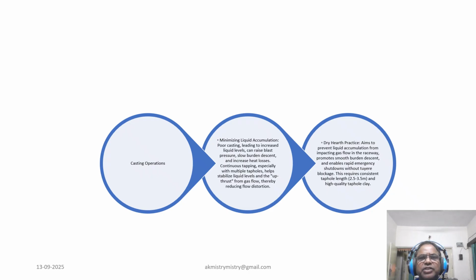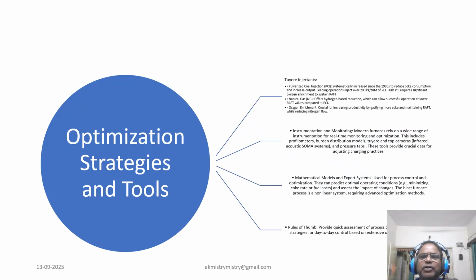Minimizing liquid accumulation is essential, and poor casting leading to an increased liquid level can raise blast pressure, slow burden descent, and increase heat losses. Therefore, continuous tapping, especially with multiple tapholes, keeps a stabilized liquid level and reduces upthrust on the gas flow, thereby reducing flow distortion. And thus we come across casting operation as one of the very important aspects to take care of for our furnace consistency.